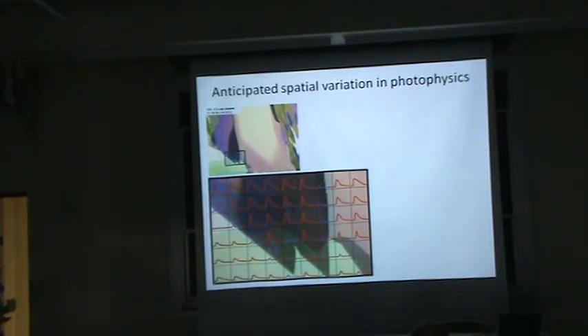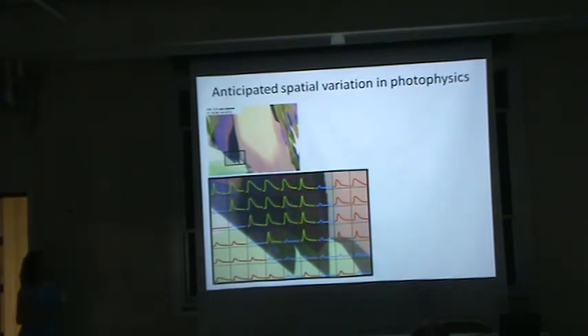And to try and highlight that, if you look at these blue traces right here, they correspond to boundaries between domains, where maybe these boundaries act as little electronic abysses. Okay, maybe excitons disappear or get pinned at these boundaries. And so we have very little signature of them showing up anymore. Or you could imagine looking at this one domain where you have similar amplitudes to all of these traces, but the widths are different.